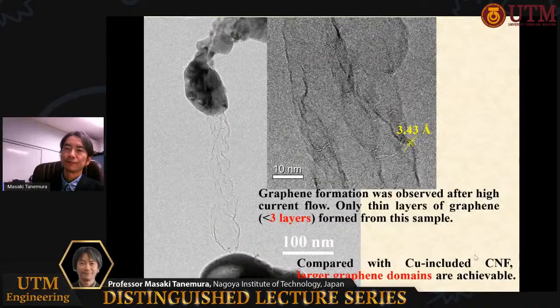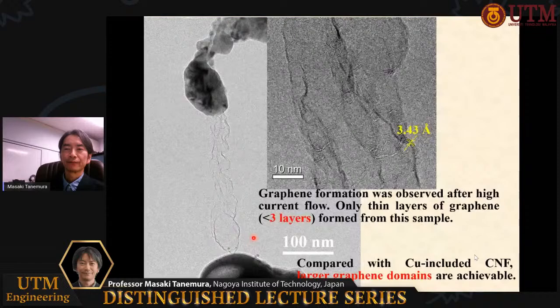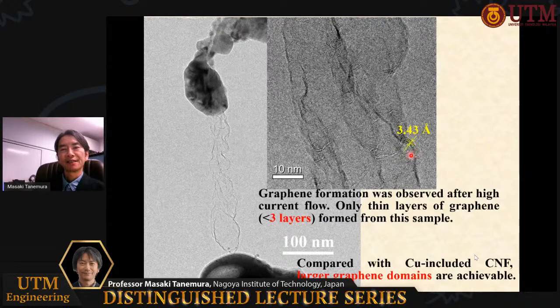This is the enlarged image of the graphene nanowire. The graphene nanowire consisted of about 3 layers of graphene, and the domain size is larger than the copper-included carbon nanofiber case.